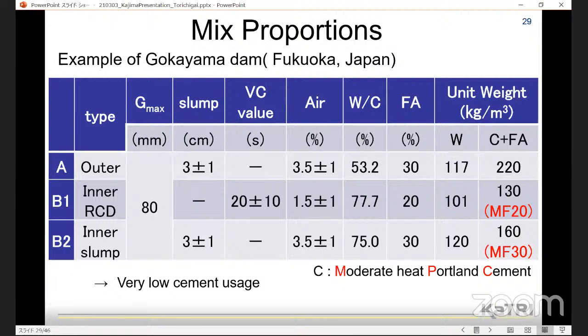The replacement weight rate of fly ash used for dam concrete is ordinarily 20% or 30% for Japanese dams. And the air content and the slump are as shown here. And the VC value is checked here.